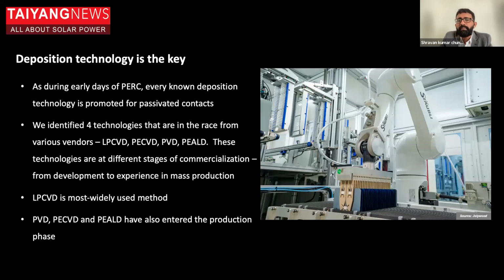So when it comes to the manufacturing of the passivated contacts, the core of the process lies in three steps, as I said earlier. So application of interfacial oxide, then deposition of intrinsic polycrystalline silicon layer, and doping the polysilicon.